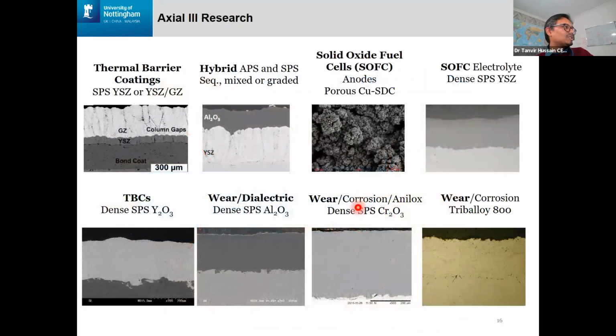More examples of what the axial plasma can do: it can produce multi-layered structures. This one is a gadolinium zirconate structure over yttrium-stabilized zirconia, on a MCrAlY bond coat, and underneath that a nickel-based superalloy. So all of these are multi-layered systems. Similarly, it can also produce alumina, a much denser alumina. For solid oxide fuel cell guys, it can produce electrolyte, which is much denser, and also porous anode, where you want porosity. A whole range of applications, from functional coatings of yttria as well as alumina.